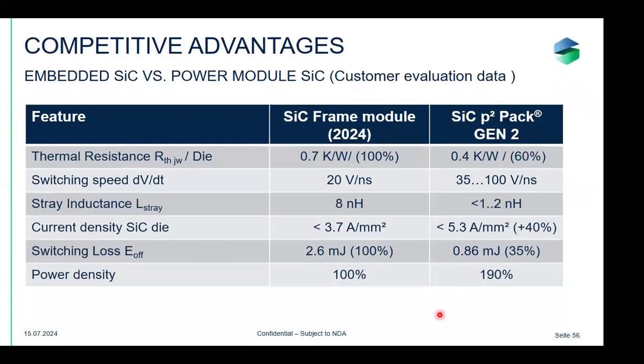And now I come to an overview to show the competitive advantages. We did this together with a customer who is also doing modules himself, and who brought a new module to the market this year. So it's a really current module, and they did a one-to-one comparison of the technology: a silicon carbide frame module against our silicon carbide P-square pack in generation 2. What they found, even though they used a silicon nitride ceramic substrate, was 0.7 kelvins per watt per die. If you put this as 100% and compare it to what you can achieve in an embedding with 0.4 kelvins per watt, it's only 60%. So you can again achieve better heat dissipation out of a generation 2 P-square pack in comparison to a frame module.